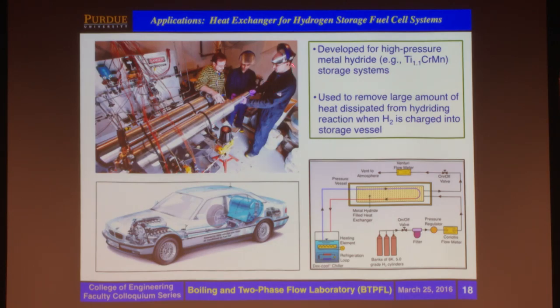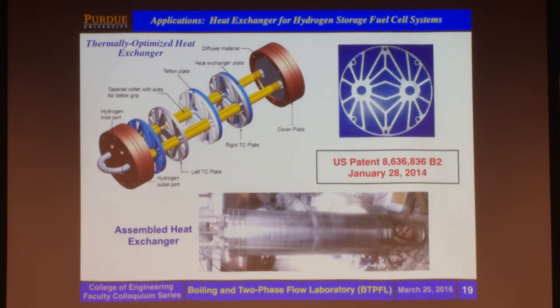At Zucro, we also did work related to hydrogen storage fuel cell systems. Here we're talking about storing hydrogen in high pressure metal hydride. You supply the hydrogen and store it by reaction with the high pressure metal hydride. The problem with this is that you produce an enormous amount of heat over a very short period of time. And we developed three different heat exchanger designs for this purpose, highly optimized thermally. And here you have one of them. You could see the shape where the heat exchanger is optimized so that you fill the cavity with the hydride. And these are the cooling ports on the inside.